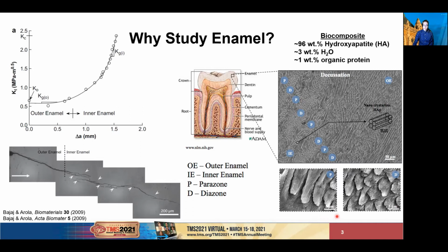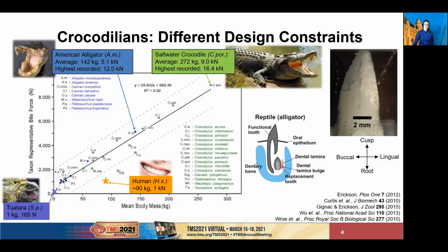At the smallest level, it is made of hydroxyapatite nanocrystals that are assembled into prisms or rods, which then stretch continuously from the dentin enamel junction to the outer enamel surface. It is the interface between prisms that is responsible for much of the crack resistance. In the inner two-thirds of the human enamel, the rods weave in decussation bands, further helping to guide cracks. This helps our teeth withstand millions of cycles over a lifetime of use, but crocodilians have some different design constraints and very different enamel structure.